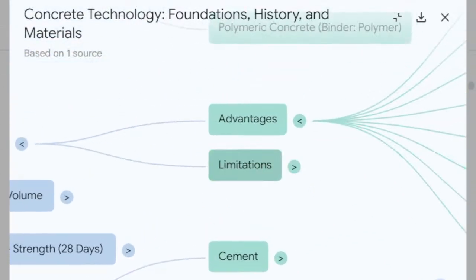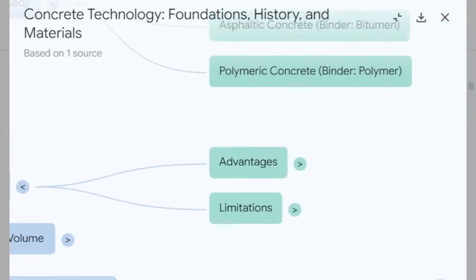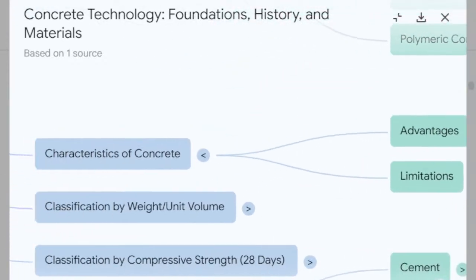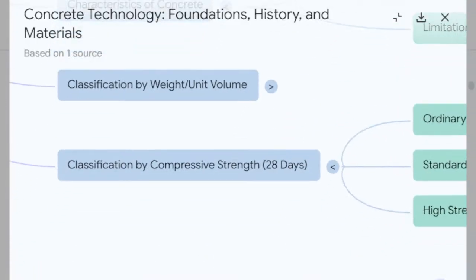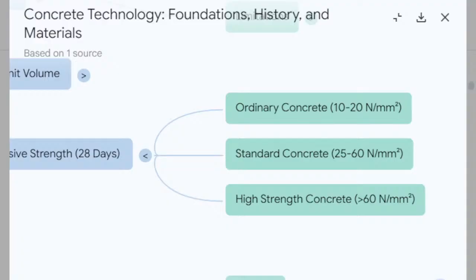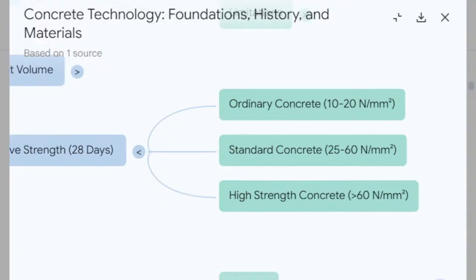And finally, anything significantly above 60 N/mm² is generally considered high-strength concrete. This is reserved for more demanding structural elements. Think of the slender, heavily loaded columns in very tall skyscrapers, or elements in long-span bridges, or specialized applications where you need a high strength-to-weight ratio, or where space is really tight. Engineers are constantly pushing these boundaries, developing ultra-high-performance concretes now that can exceed 150 N/mm². That sounds like a lot of pressure. It is. Imagine roughly 600 kilograms of force pressing down on an area the size of your fingernail.